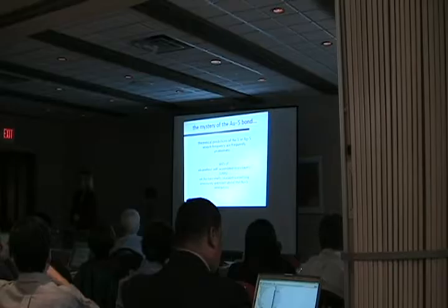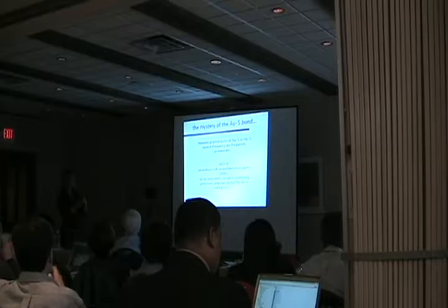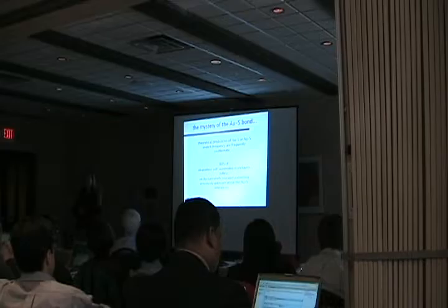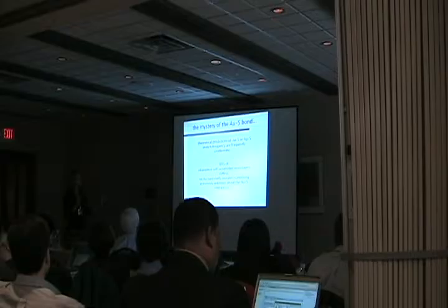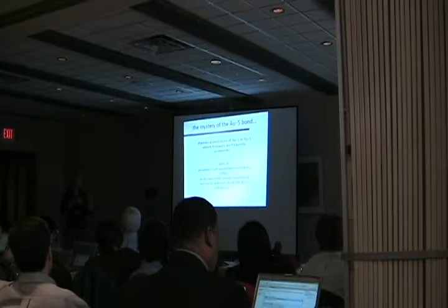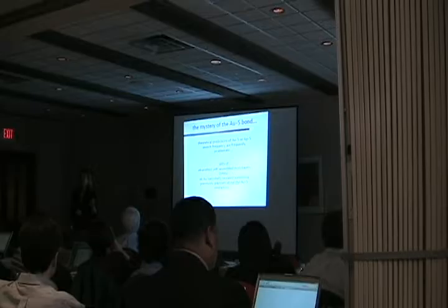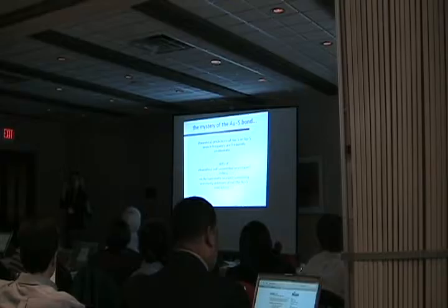If you ask a quantum chemist to calculate a surface enhanced Raman spectrum, they'll get all the modes correct within a wave number or two. They're in very good agreement, unless there's something unusual about the system, except for one mode, and that mode is the metal-sulfur bond, the bond that attaches the molecule to the metal itself. I'm only talking about those sorts of systems. If you have a gold-sulfur stretch or a silver-sulfur stretch, all of your spectrum will be perfect except that one mode, and that mode will be off by 30 or 40 wave numbers. It will be red, it will be blue, who knows?